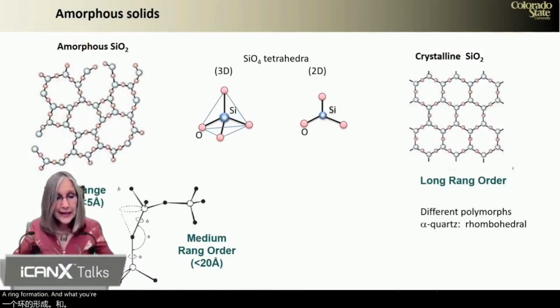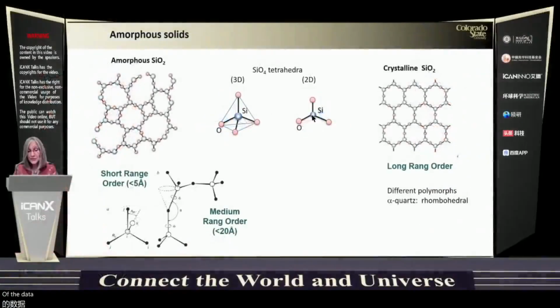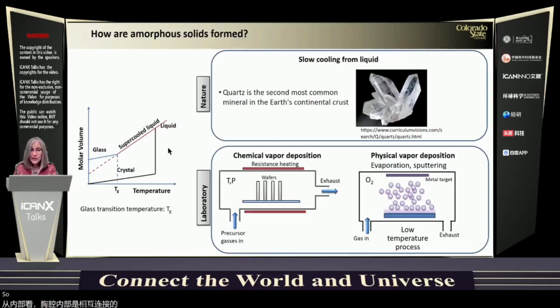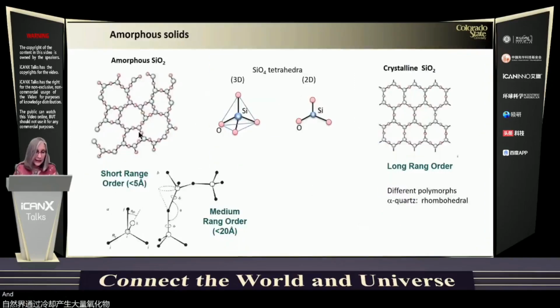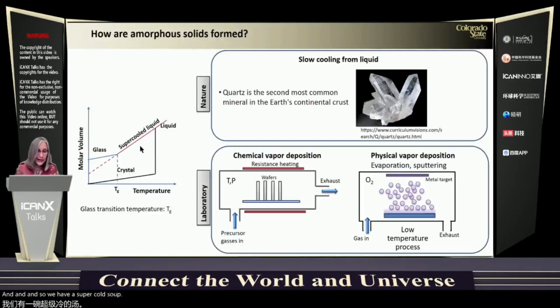And what you are seeing here is the picture of the tetrahedra just seen in 2 dimensions, connecting to each other. So nature makes amorphous oxides by cooling very, very slowly. And so we have a supercooled liquid that essentially at a given temperature becomes so viscous that it solidifies. And this is what we call the glass.